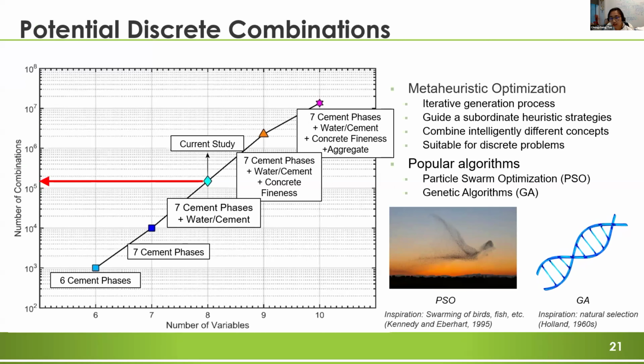Both VCP and VCCTL models are full of parameters, including different cement phases, concrete aggregates, and the operational conditions inside the kiln. With the increase of the inputs, the total number of combinations will increase exponentially. So for my study, I selected 8 inputs, including the 7 cement phases and 1 water to cement ratio parameter. So we can see that the total number of combinations is about 10 to the 5 different simulations.